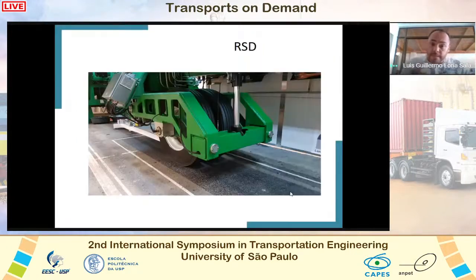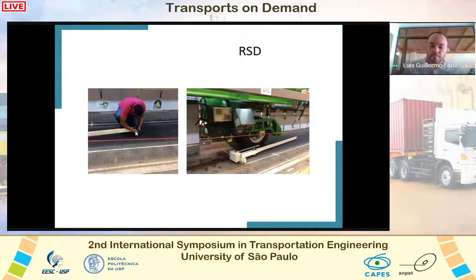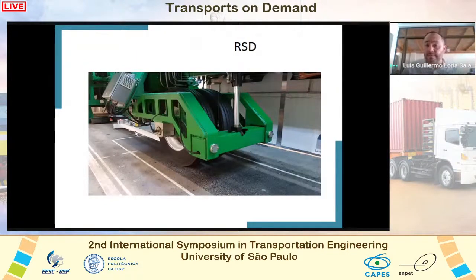So the test development, the RSD: it's basically a laser that is put over the test carriage, and you can see it over there. It is this type of deflection measurement, like a Benkelman beam. We measure with the RSD every single day in order to know the damage for each day. We also have falling weight testing, but the situation is that you cannot move the falling weight machine every day. So the RSD does this work.